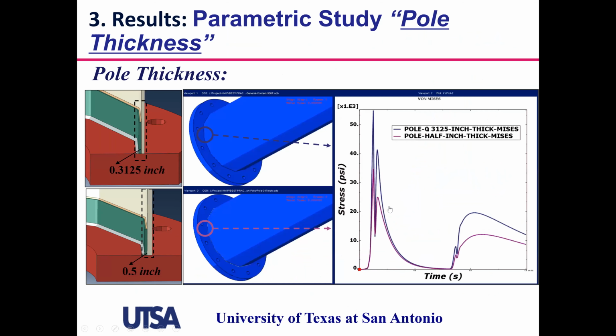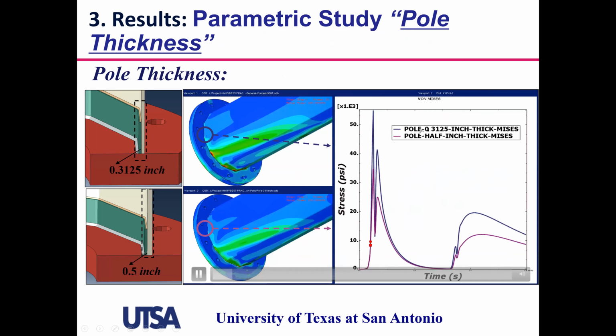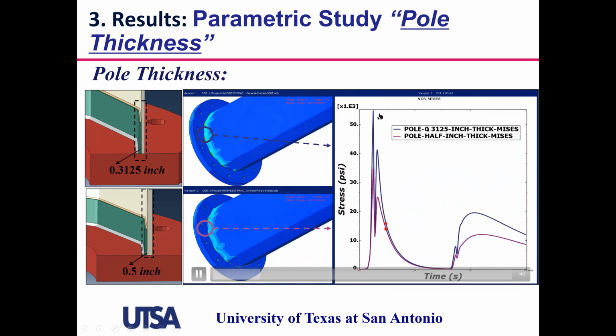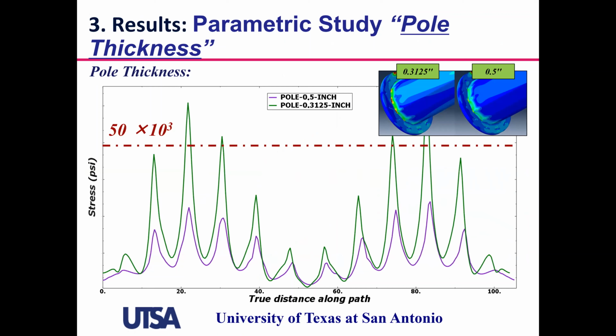Then we compared the effect of the pole thickness by keeping the base constant. And from here, we can observe that if the pole thickness is lower, then the stress demands are going to be higher. In the interest of time, let me move on to the next slide, which shows similar information, in which a lower thickness corresponds to higher stress demands during galvanizing.